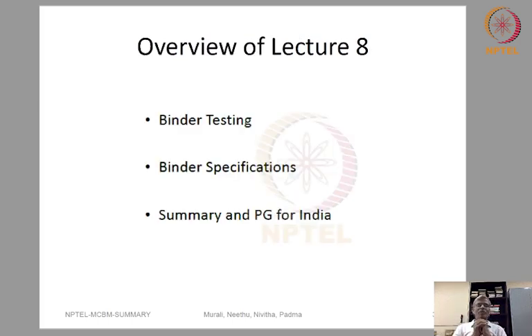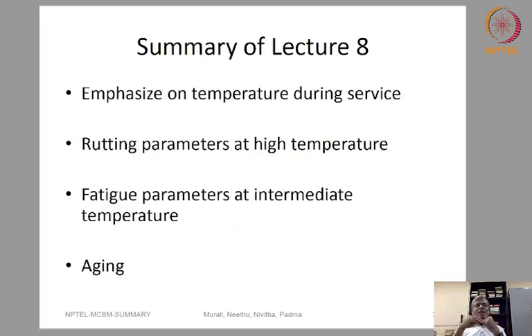So I looked into it from the binder testing protocol, binder specification protocol, and what we will be doing in fact if we write PG for India. So the main emphasis here is that you have to emphasize temperature during service. And in fact, please go back and take a look at ASTM D6373 as well as IS 73. The specifications are written in a completely different way. In one case, the temperature is listed on the left hand side and the spec values are written on the right hand side. In the performance grading, the spec values are written on the left hand side and the temperature is written on the right hand side. So we talked about rutting parameters at high temperature, fatigue parameters at intermediate temperature in addition to aging.